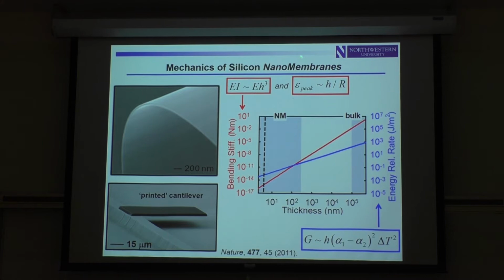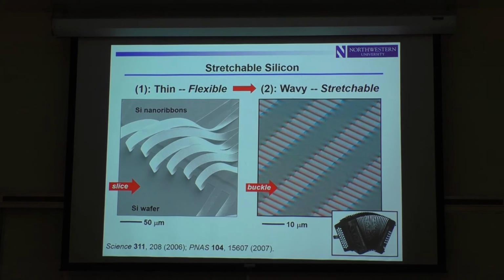So silicon nanomembranes are interesting because they're flexible, they're floppy, and they're sticky at some level. And so if you take that kind of idea, then it becomes a question, where are you going to get the silicon nanomembranes? And it turns out there are materials, etchants, that will allow you to slice very thin but highly perfect, from a crystallographic standpoint, sheets or ribbons of silicon off of a silicon wafer. So it turns out you can do that. I won't get into the details, but it's very straightforward. So you have a sort of device-grade class of silicon in ultra-thin format, still thick enough to support all the kind of electronic functionality you need, but thin enough to offer these kind of mechanics and adhesive properties. So that gets you flexible.